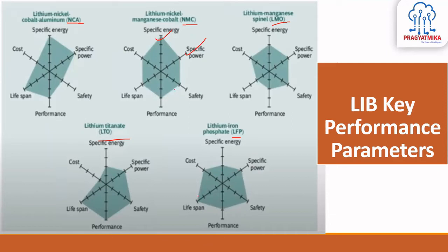For example, the LFP chemistry and the NMC chemistry are very good competitors to each other. We can store higher energy in the NMC lithium ion chemistry compared to LFP, and it has a higher discharge rate. Whereas if power is concerned, we can take a higher specific power from the LFP chemistry compared to the NMC. On the safety aspect, the LFP is safer in operation. It has less specific energy, and the oxidation doesn't happen. So that's why it is a safe chemistry compared to the NMC.